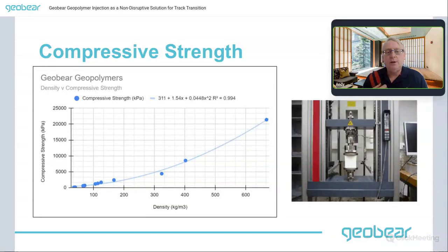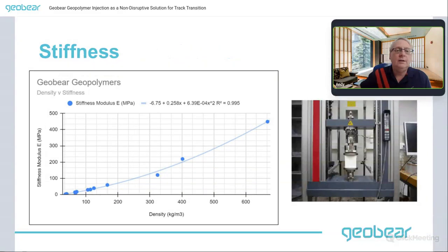When you look at the compressive strength of geopolymers, you can see that the strength increases with the density. That means there are fewer gas bubbles and more resin per unit area, and so you get an increase in strength. More resin, more strength. The same thing is true for stiffness or Young's modulus. As the density increases, you get an increase in stiffness, really just because there's more resin versus bubbles of gas. So when there are very, very small amounts of gas present in bubbles, you have maximum strength of the material.